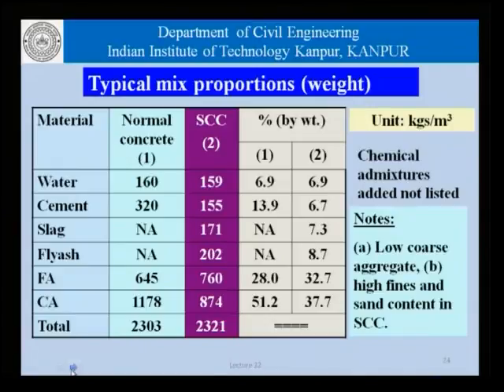Now, if we look at the typical mixed proportions by weight of normal concrete and of self compacting concrete, these numbers here are those for a normal concrete, and these numbers are for a self compacting concrete. Now, if we look at these numbers, these are the proportions in mix 1, that is the normal concrete, and the self compacting concrete, and we are able to see the proportions by weight.